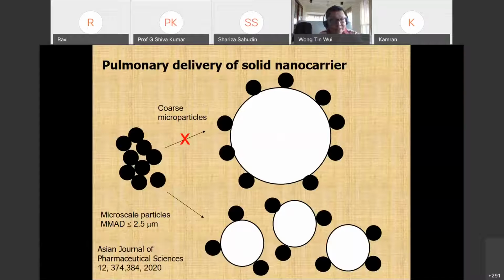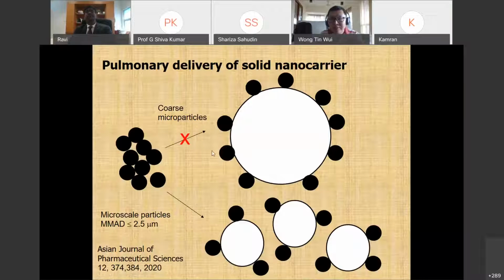Right. So on this note, we hypothesize a possible way to deliver the nanoparticles with better capacity. If you read through the articles of the past 20 years, the small particles are usually deposited on coarse microparticles. This coarse particle will then be inhaled in order to deliver the drugs into the deep and peripheral lung. Note that the coarse particles have a size of 200 to 300 micron in general. So more often than not, the nanoparticle will not be able to detach from the coarse microparticle. And coarse microparticles, being a few hundred microns in size, will not be able to reach the deep and peripheral lung. They are usually situated at the back of the throat. So when this occurs, there will not be any possibility for the nanoparticle to be inhaled into the deep and peripheral lung.